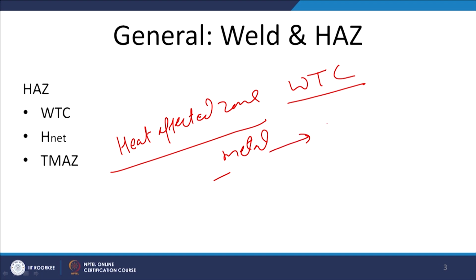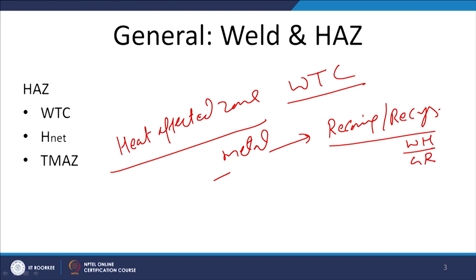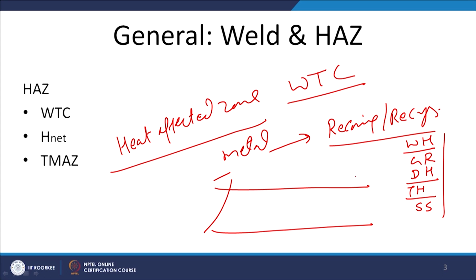It may experience recovery and recrystallization in the case of work hardening metals, grain refined metals, dispersion hardened metals, even transformation hardened metals, and solid solution strengthened metals. So, it is very common that the heat affected zone, due to the weld thermal cycle, will experience recovery as well as recrystallization, but thereafter the metallurgical transformations